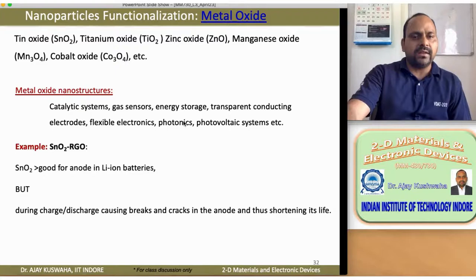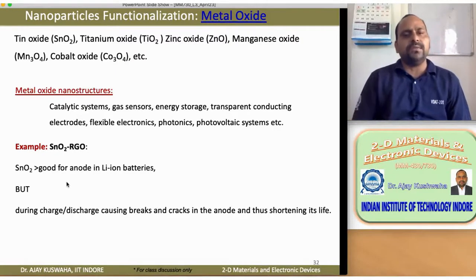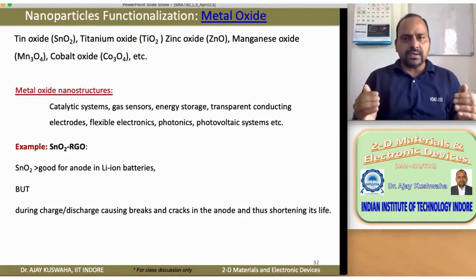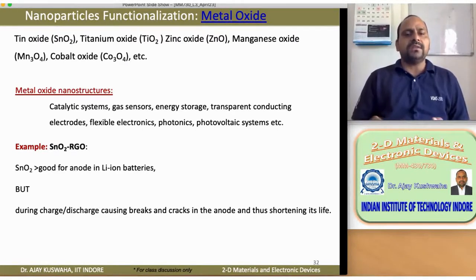So that was the target. So here one example we can see, when the reduced graphene oxide is modified or functionalized with tin oxide nanoparticles. In this study, they have shown that if only tin oxide is used as an electrode material for lithium ion batteries, this is not so good. There are some issues. During charging and discharging, this material usually breaks or cracks appear at the anode. And if cracks are there, then it is going to reduce the life of the battery.